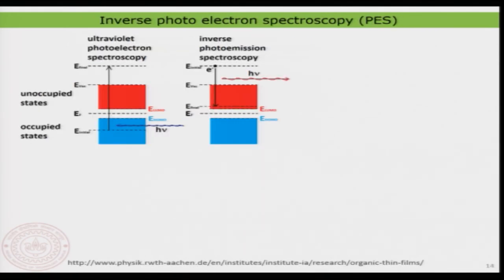Now, what I also want to show you is that you can not only measure ultraviolet photoelectron spectroscopy by removing an electron, you can also do the opposite by injecting an electron into one of the electronic states. By injecting an electron into a given level with a certain energy gap, you can get a photon out of the material, because the photon corresponding to that particular energy would be emitted by the material. So, you can inject electrons into the material and then look at the photoemission from the material, and that is something known as inverse photoemission.